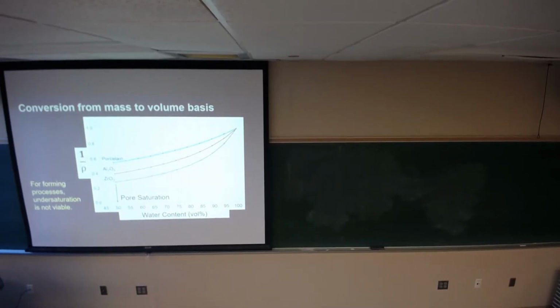We learn things from the shear cell, but I can't take a plastic body and put it in the shear cell and say, oh, I know that this is going to be a good body for extrusion, because I will measure the same thing every time. I'll have a low cohesion stress in the system or a very small variation in cohesion stress based on conditions. But all those will have a zero pressure dependence, because now when you press on the system, you have water filling the pores, you get a hydrostatic pressure case, and there is no drag on the system because water is incompressible. So applying pressure does not increase the friction in the system, as long as my pores are saturated.